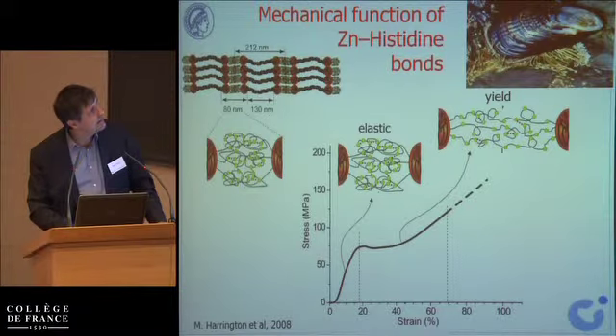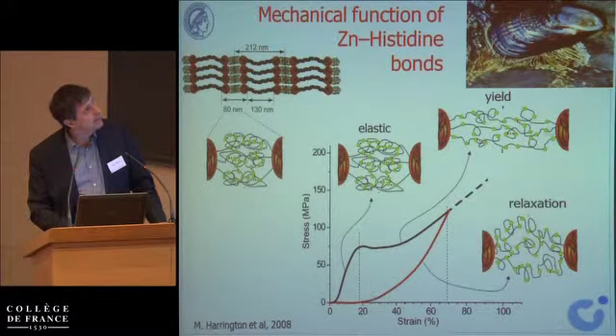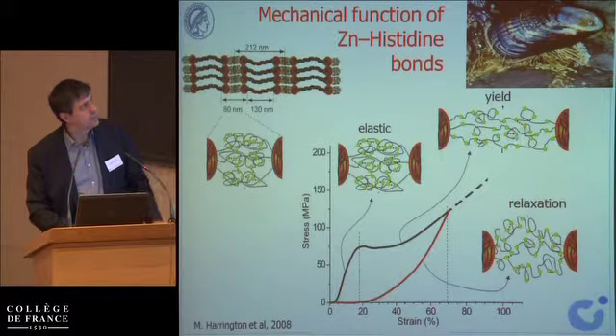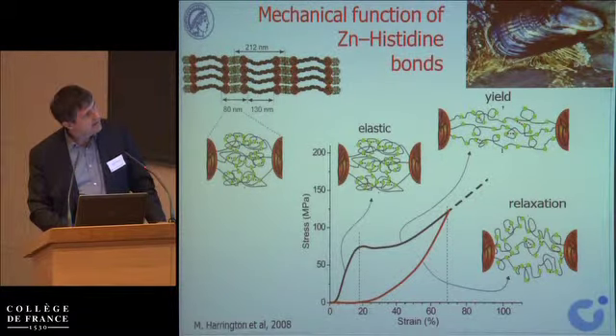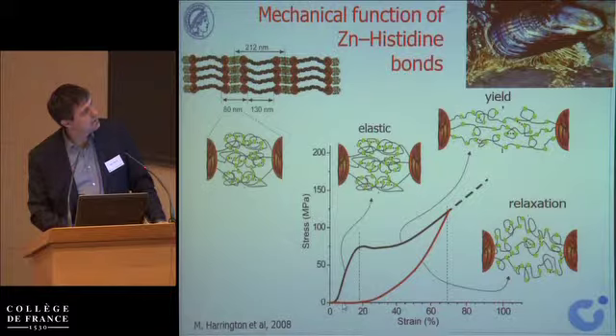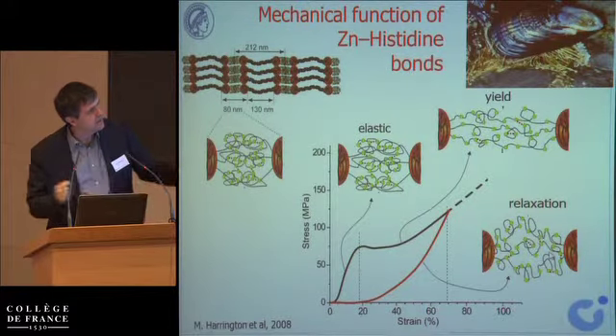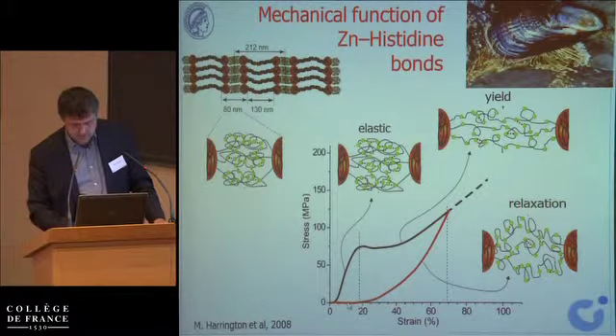So this zinc cross-links these little bonds here, and on unfolding, of course, the covalent chain that goes from one end to the other is still holding. You have broken all these red bonds, but you haven't broken the connection between the two ends, and this is what some people call sacrificial bonds. And on the way back, the sacrificial bonds are still broken. So now if the whole thing folds back, it has a very, very small modulus, because now it's just the unfolding of the protein that holds back. So it has lost its properties.